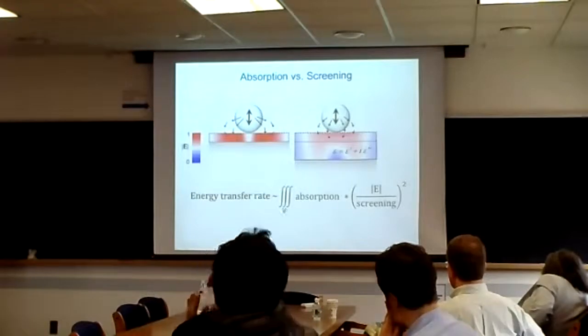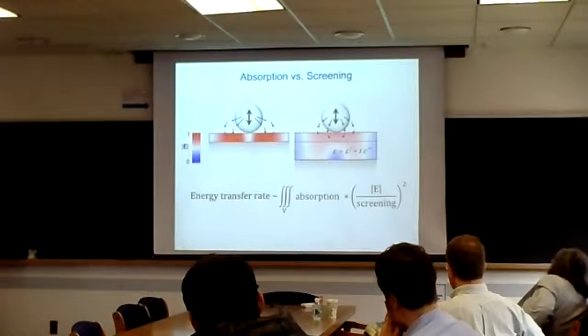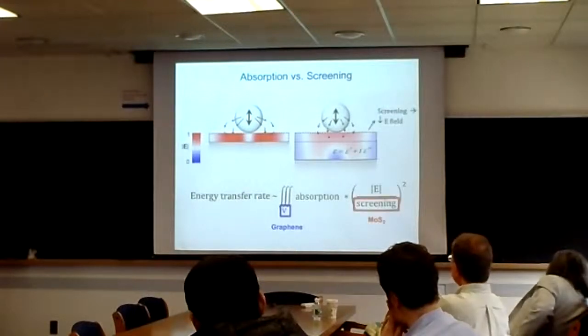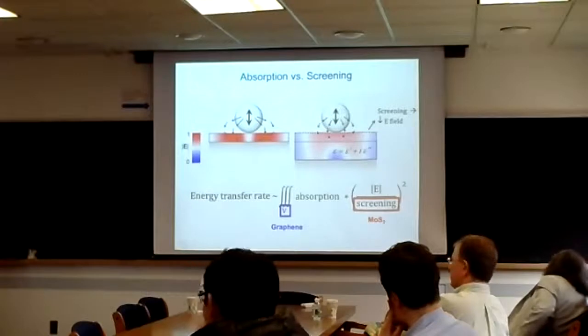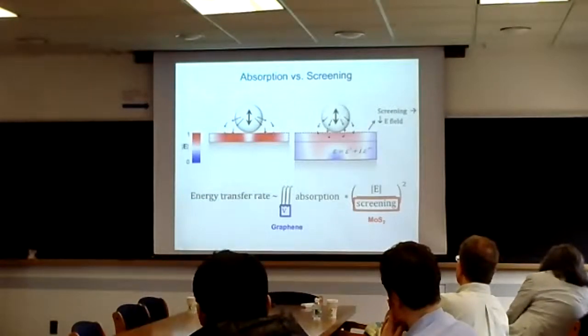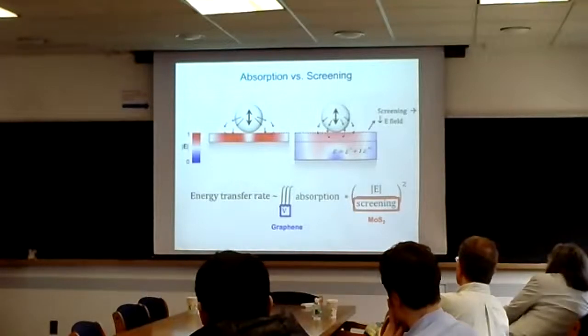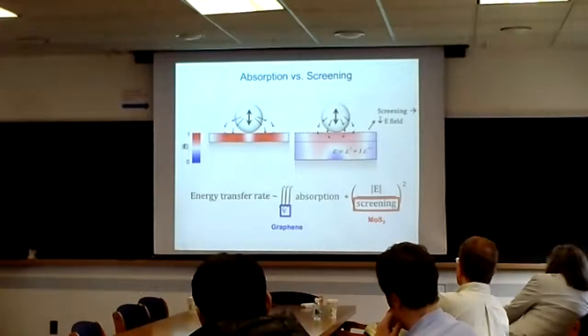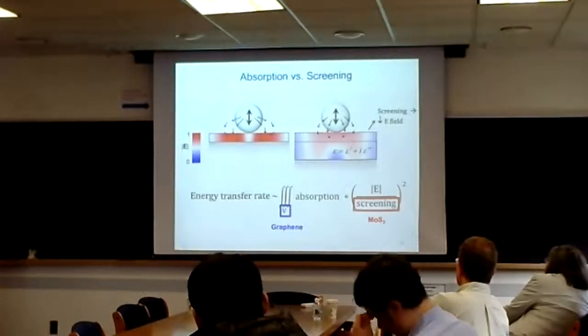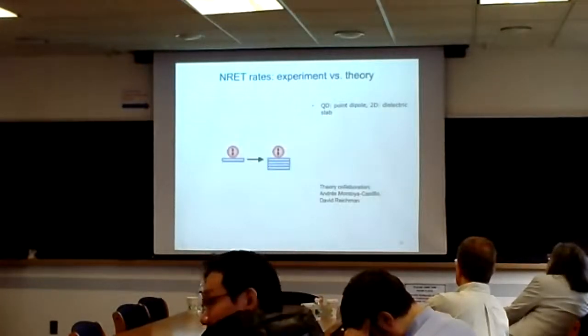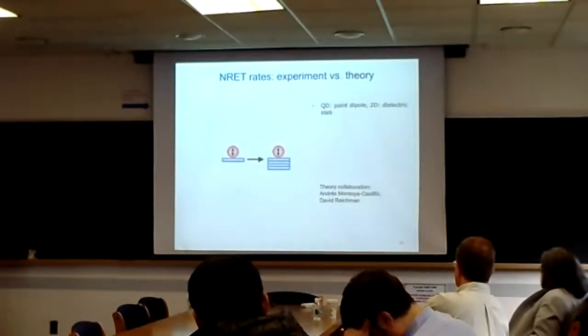Now, in a very naive picture, if you think of energy transfer as the dissipation or absorption times the square of the screened electric field, as you increase the volume you're increasing this integral, and so your energy transfer rate goes up. But in the case of MoS2, the addition of even one more layer reduces this field by such a great amount that the increased number of decay channels you're adding doesn't help. In graphene, sure, the field can go down a bit as you increase the number of layers, but overall what wins is that you have more absorption underneath. But in MoS2, even adding one more layer screens the field so much that you are losing from the start.